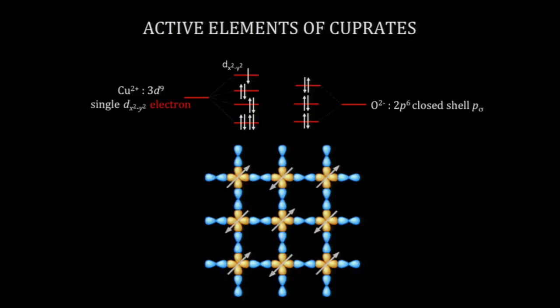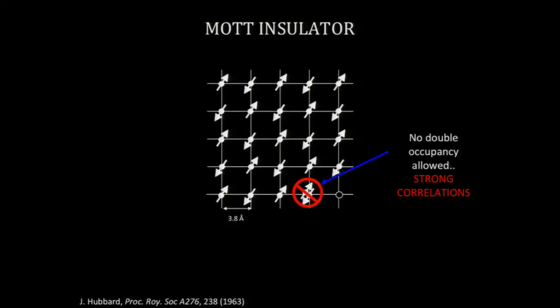But the basis for the cuprates lies in this structure here. You have copper atoms surrounded by oxygen atoms. And once they hybridize, what you really have is one electron left in the dx squared minus y squared orbital. And you look at that as a half-filled band. You'd say this should be a metal. It turns out it's not a metal. It's what we call a Mott insulator. And the reason for that is that the Coulombic repulsion on any given copper site, when you try to doubly occupy it, is so huge that it suppresses that motion. And so what you really have is an insulator. And in fact, you have an antiferromagnetic insulator.